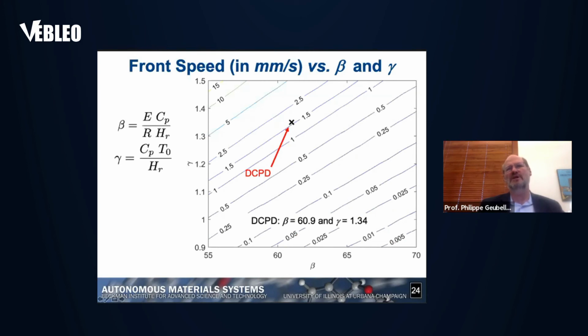You can actually plot the predicted speed of the front in millimeter per second. So DCPD has a value of beta of about 61, value of gamma about 1.3, would be right over here, has a speed of the front at about 1.5 millimeter per second. If I want to go faster, right, I want to go to the top left of this particular diagram. So that means two things.